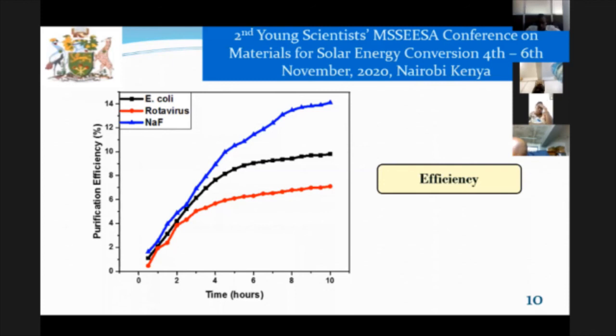So the above concentrations are way above the recommended levels. As we know, the recommended levels for sodium fluoride are 1.5 milligrams per liter, and then the one for E. coli we actually need more than 99.9% efficiency in purification, and the same thing for rotavirus.